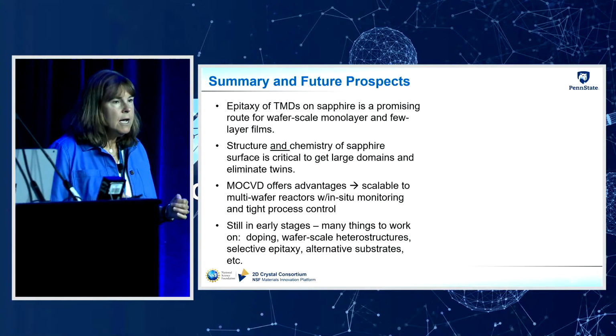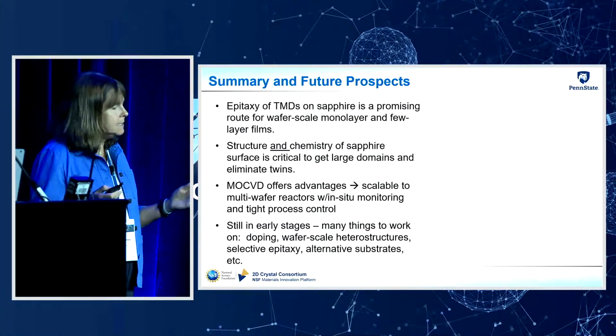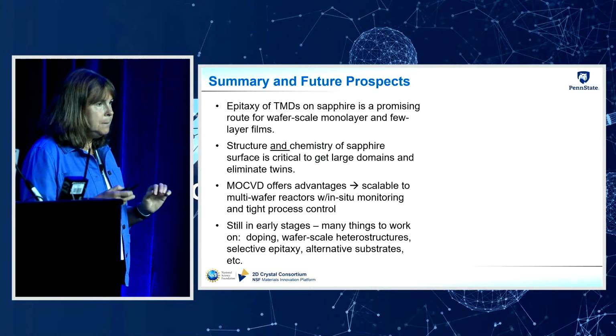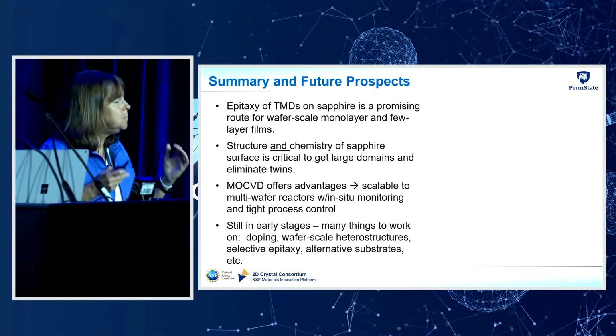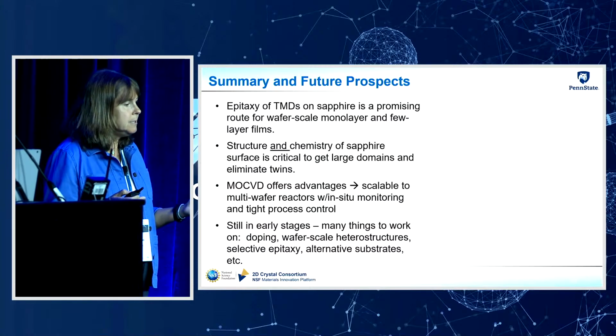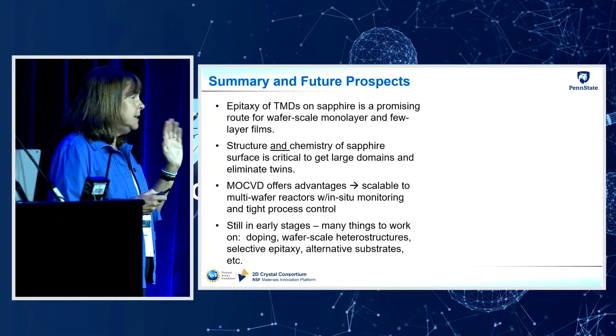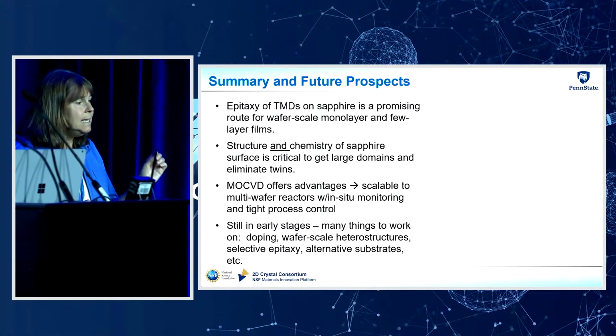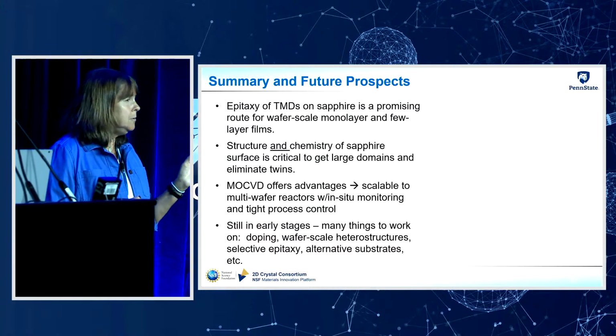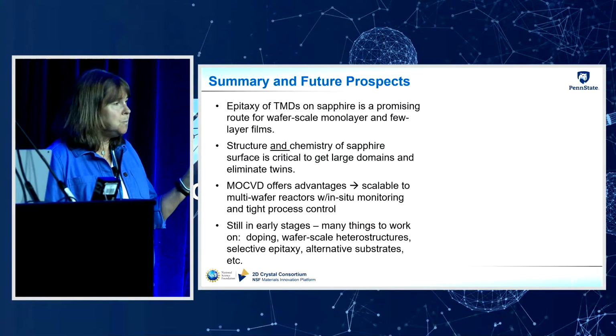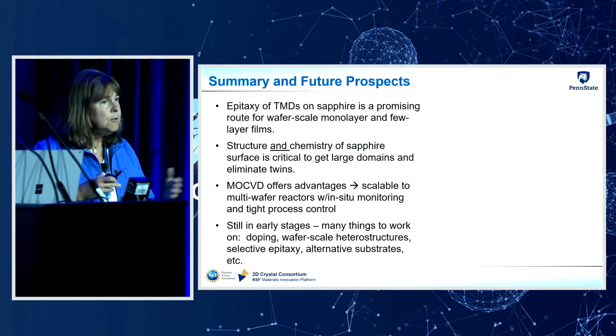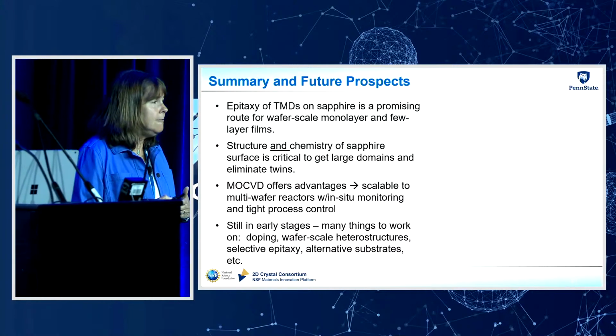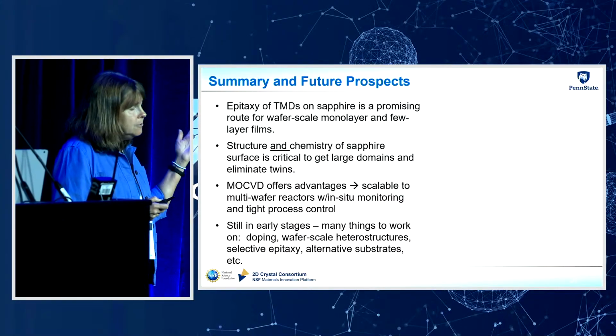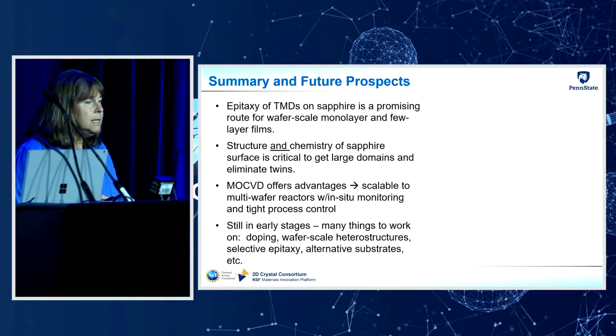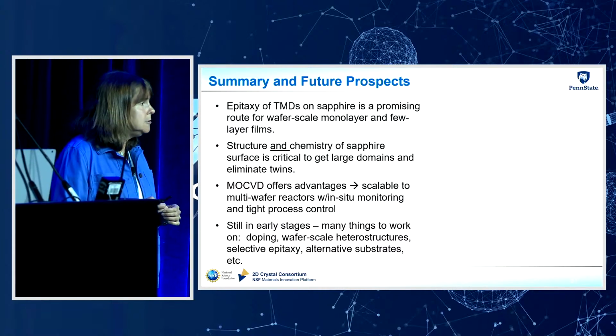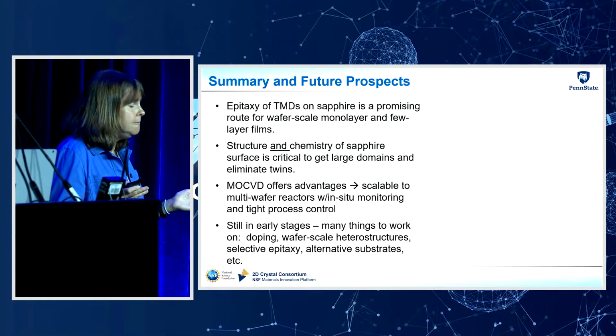Okay, so to finish off, I just want to summarize where things stand. So epitaxial growth is a really promising approach to be able to produce wafer scale monolayers of 2D materials. However, understanding the fundamentals of the synthesis process are really key. As I showed you, we need to control both the structure of the substrate that we're growing on as well as the chemistry of the substrate surface. They're both critical in order to get films that have high crystal perfection. We use MOCVD growth. So MOCVD is a technique that's compatible with semiconductor manufacturing. It's widely used for III-V films.